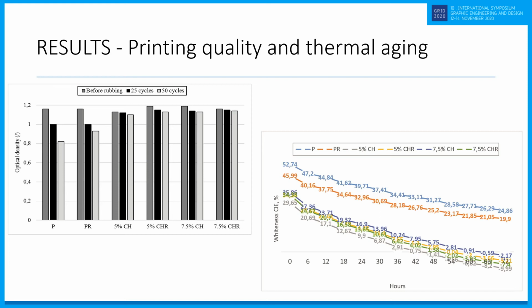In our study, we used the TAPPI standard for determining the printing quality of our sample papers. As you can see in the picture on your left side, after 25 cycles, the papers with chitosan and rice starch achieved better quality compared to other papers. Before rubbing, the highest optical density was in the paper with 5% chitosan and 7.5% chitosan and rice starch. The highest concentration of the filler gave the most stable color resistance after rubbing of 50 cycles. As expected, fillers increased color stability compared to the paper sheet where fillers were not used.